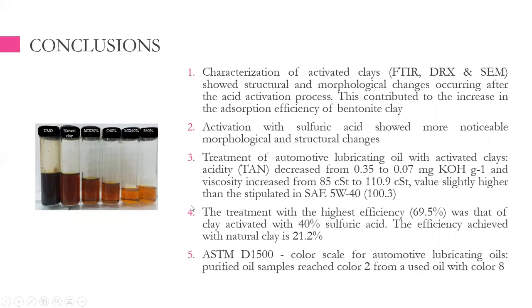We didn't show these results, but we also determined the total acid number of the treated used motor oils, and this number decreased from 0.35 to 0.07 when we used the clays that were activated with sulfuric acid. In this case, the viscosity of the treated oil also increased from 85 to almost 111 centistokes. And this also shows the efficiency of the contaminant removal process using these activated clays.